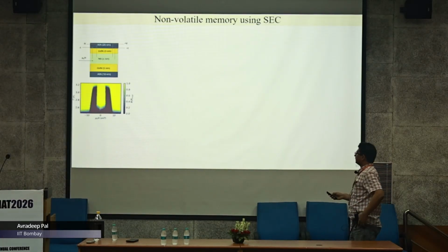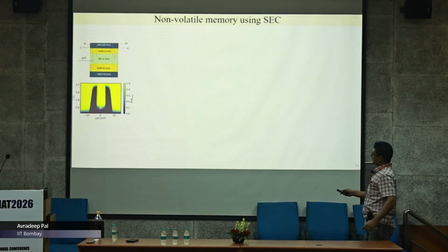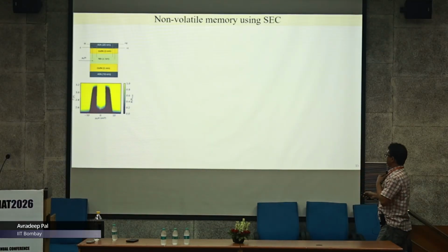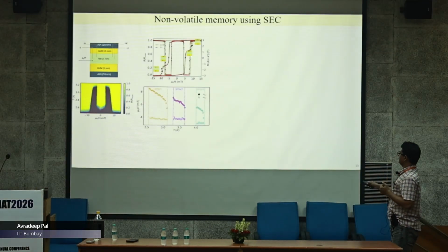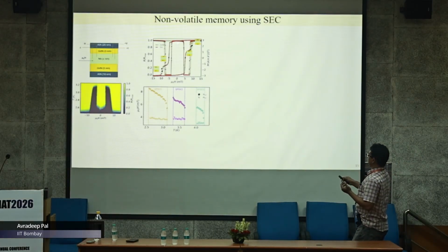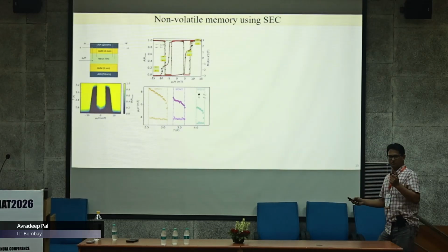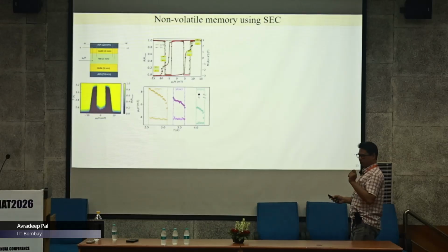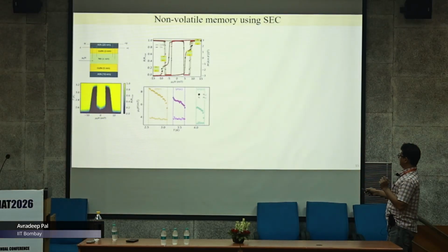Sorry for that interruption. So again, gadolinium nitride, and we have niobium over here. What we realize is that, if this is the magnetoresistance response of the system, then you can initiate the superconducting state and you can switch off the magnetic field. When you initiate the superconducting state at the antiparallel field and you switch off the field, the superconducting state should stay, okay? I should be able to hold the superconducting state at zero magnetic field.